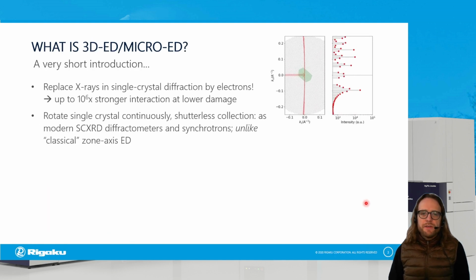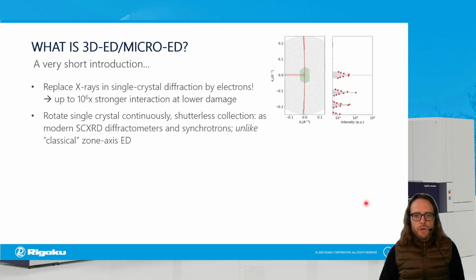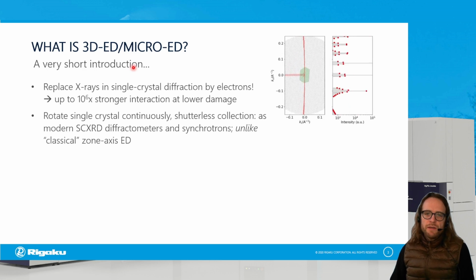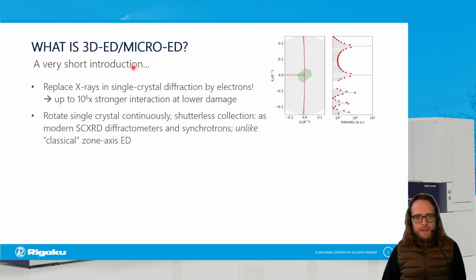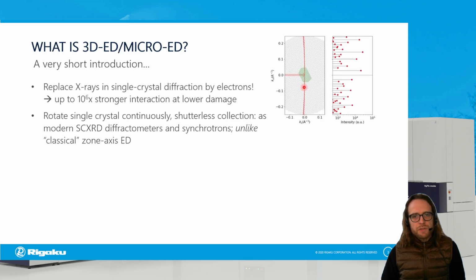This technique specifically is called 3D electron diffraction or microelectron diffraction, two terms which you can pretty much use interchangeably. So the measurement scheme is nowadays really exactly the same as you would be used to from a state-of-the-art X-ray diffractometer. So you have a crystal that you rotate continuously inside a beam, and you have a shutterless data collection on a detector. And due to this very, very strong interaction, you get a sizable amount of signal inside your Bragg